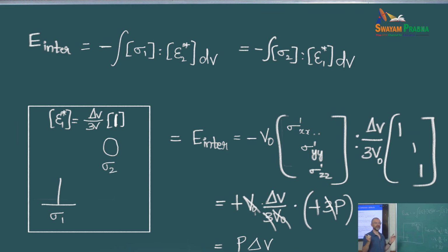We mentioned in the seminar yesterday that a screw dislocation does not create pressure; it only creates shear. So a perfectly straight, infinite screw dislocation does not interact with a center of dilatation. Now there's this core region around the dislocation. If I'm looking at a solute inside the core region, I can still use it mathematically, but it's going to give you nothing realistic.